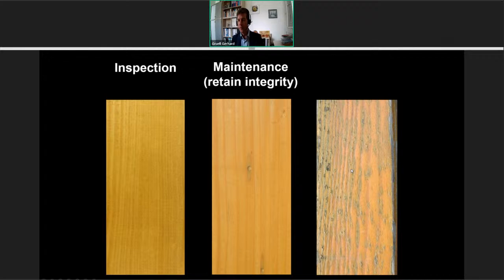But in this stage, there are really heavy defects and adhesion is lost of the coating in many areas here. This would need a repair of these defects, and that's what we call renovation is needed. So you must remove the old coating film down to the solid wood, sand the wood very well, so that all gray surfaces are removed, and then you must build up a new coating system starting from the primer. This is another kind of work, much more demanding, a lot more effort to do. That's why we call it renovation.